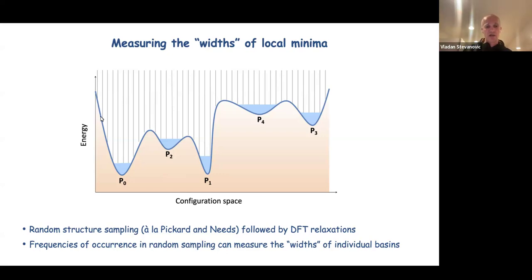So once created, these random structures will be somewhere on the slope of the potential energy surface, and then using first principles relaxations, they will relax to the closest local minimum, let's say P0 in this case. And if you do this random structure generation followed by first principles relaxation enough times, then you can just count how many times you landed in this structure, that structure, or the other one, and those counts, or the frequencies of occurrence in random sampling, would represent the measure of the width of a local minimum.